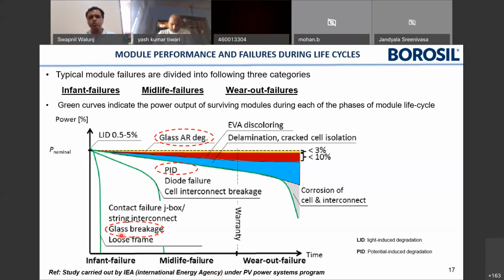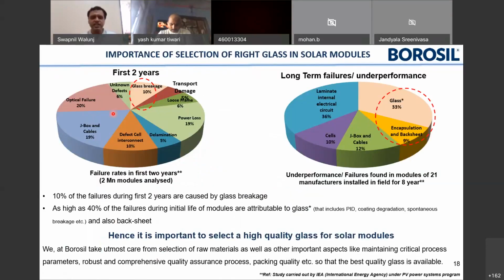In the infant failure modes, there are breakages. In the midlife failures, there are potential induced degradations, glass anti-reflective coating degradation, and glass breakages in the long term. So these things are very important as far as the life of the module is concerned, as well as the performance of the module. Just to give you the spread in terms of percentages, in the initial life, and again this is based on the IEA study, they analyzed 2 million modules aged between 0 to 2 years. In 10% of the cases they found glass breakages.